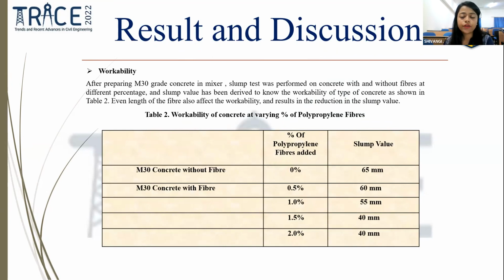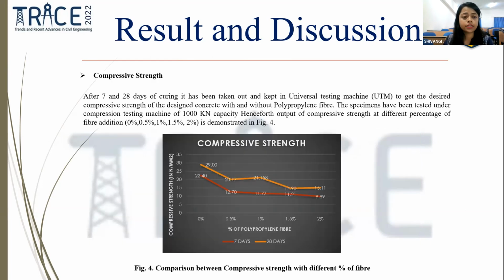Even the length of fiber also affects the workability and results in a reduction in the slump value. As we can see, when we used bare concrete, that is, without adding any proportion of polypropylene fiber, we received a slump value of 65 mm. And further, when we added fibers at different percentages, we saw our slump value start decreasing from 60 mm to 40 mm at different percentages.